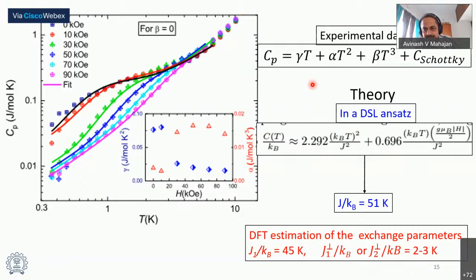Okay, and then Sumiran, based on Dirac spin liquid formalism, could work out the variation of heat capacity with temperature as coming from a quadratic and the linear term. Based on the coefficients here and comparing with our experimental data, the gamma and the alpha from the experiment, and comparing with the expected coefficients of the T-square and the linear term, actually we get a number for J over K_B, the dominant coupling in the system, about 50 K.